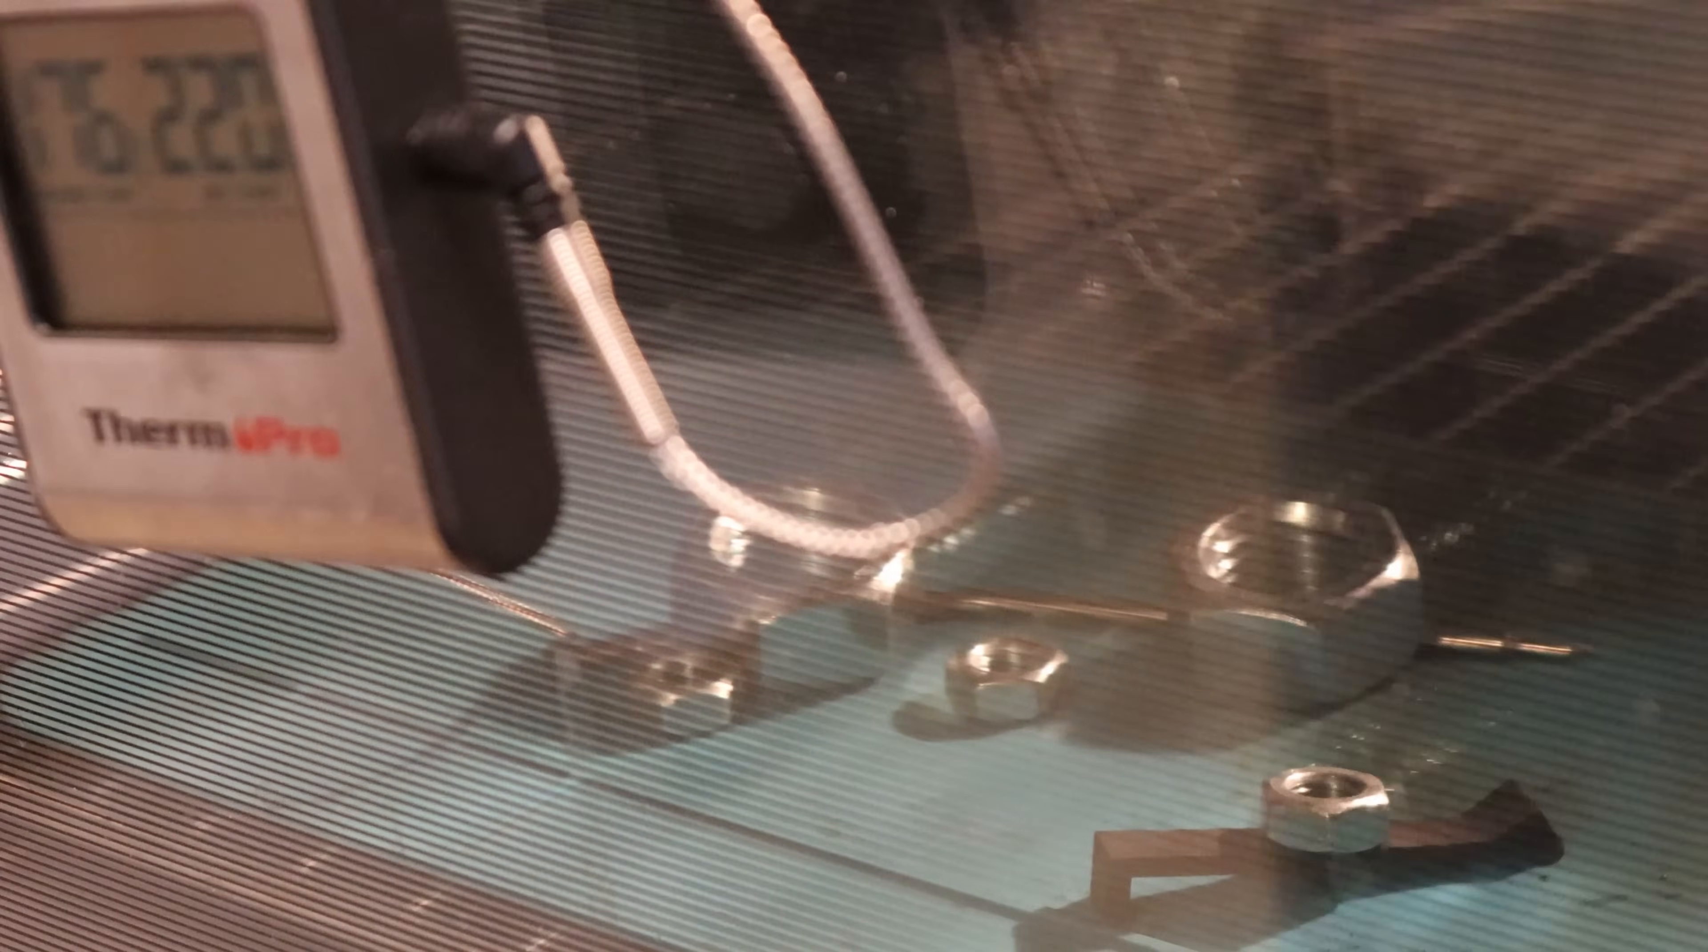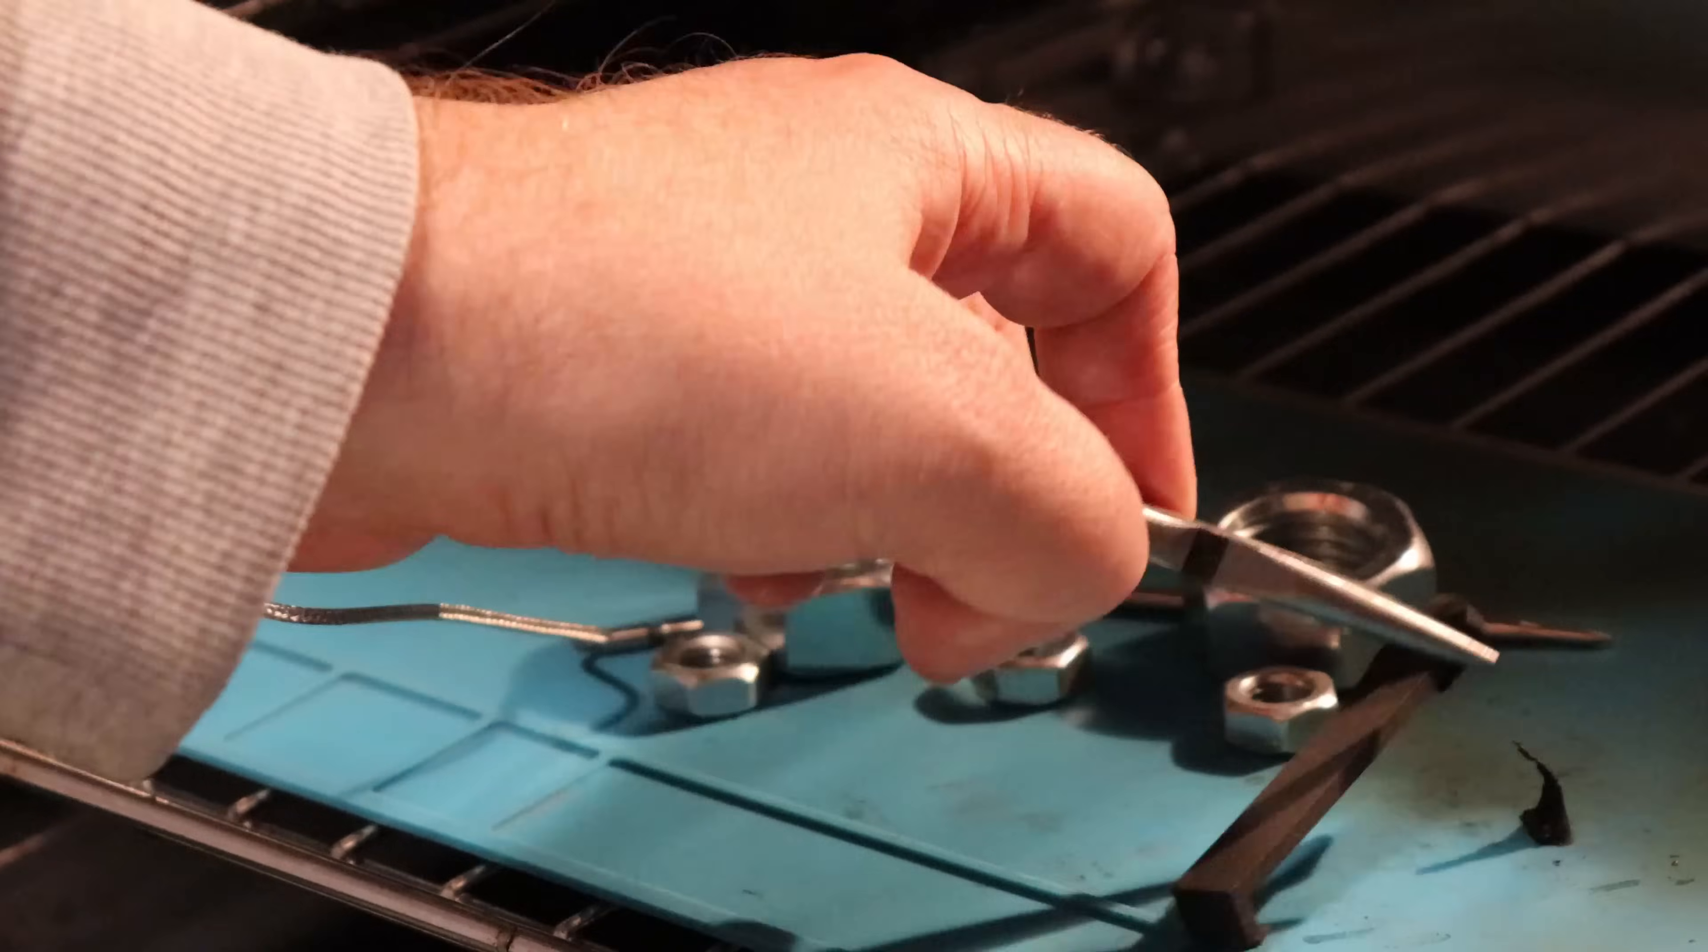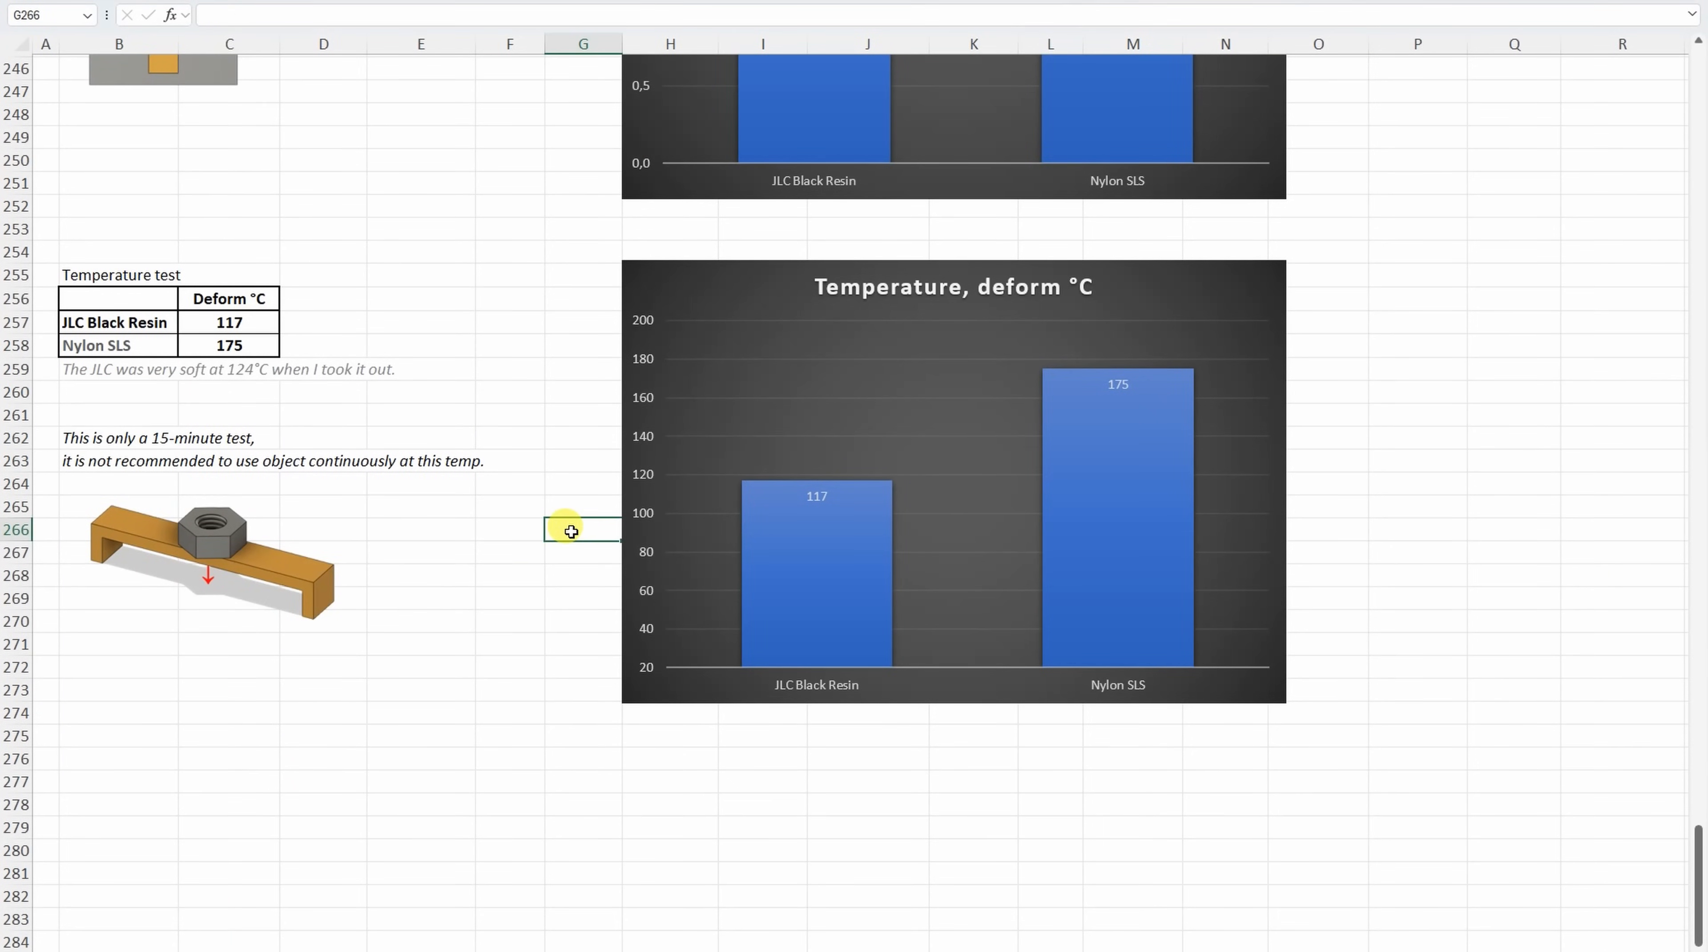Back to speed up video and I am not 100% sure but approximately on 175 degrees celsius I noticed the first deformation on this test object. 177 degrees celsius and I can see some deformation on it, I want to see how hard is this material. Ah yes. Soft. Whoa. I hope I will be able to clean this and never so sticky material. Okay. Obviously the nylon was better in this test but I'm not sure on which temperature we can use these test objects because at these temperatures I just noticed the first failure but probably the maximum is lower than this.